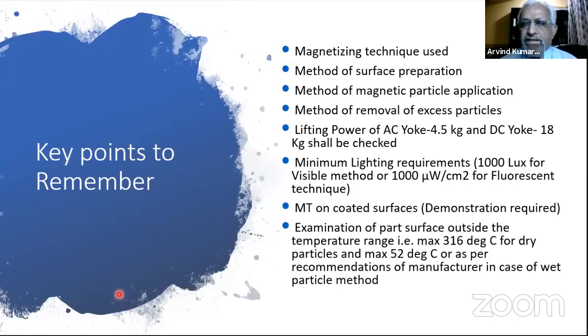Method of magnetizing the part, whether it is by yoke. Now when you're using a yoke, the AC yoke will have a lifting power of 4.5 kg. You have to demonstrate it with a calibrated weight. If it is able to lift 4.5 kg, it has good strength to be operated as an AC yoke. Similarly for DC, it is 18 kg. It has to lift 18 kg at the maximum pole spacing. Then it has good strength.